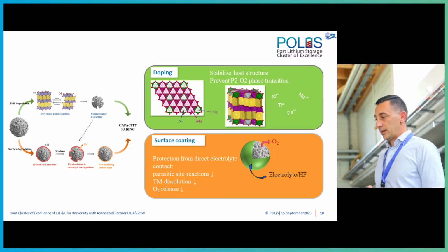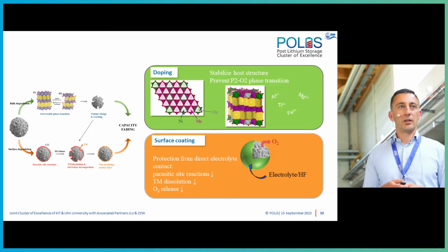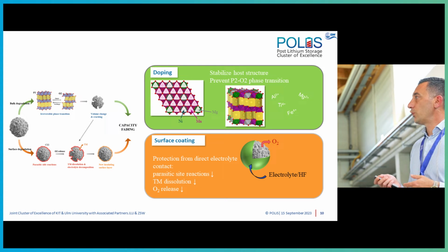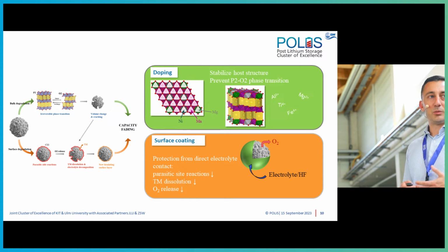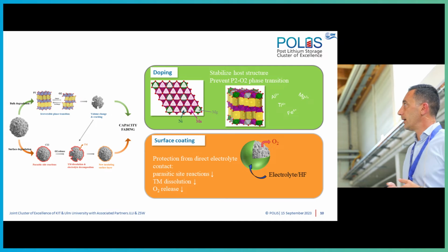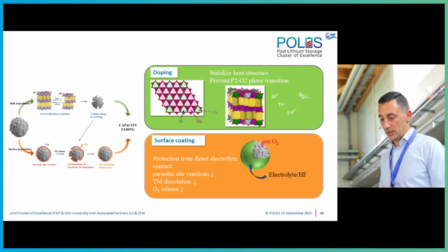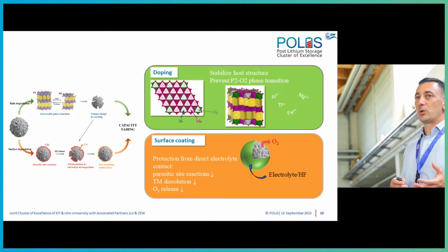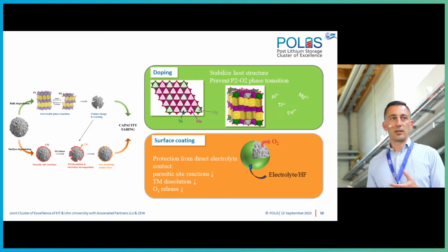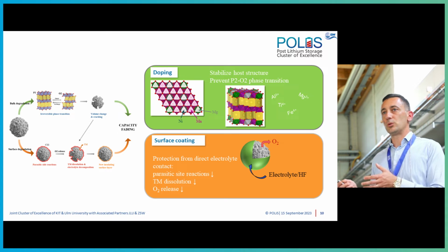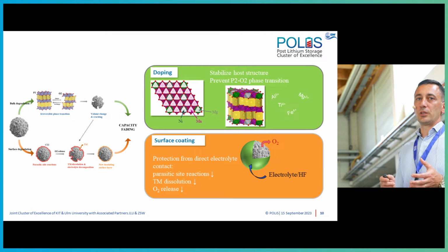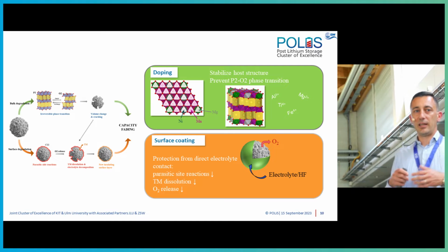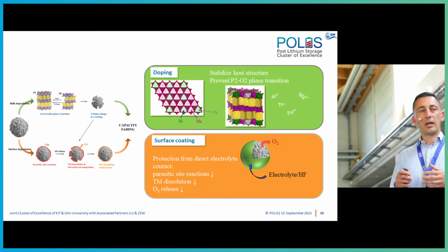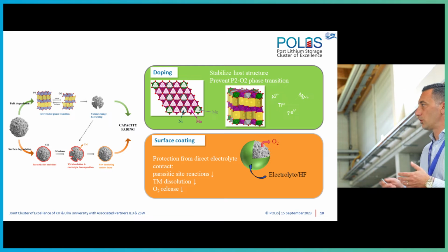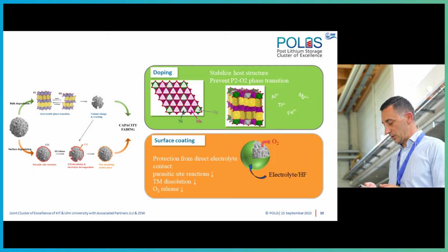Now, going back to the degradation mechanism of the layered oxides, we might come up with different strategies to mitigate the capacity fading. There have been several reports in literature for doping, but also for coating. Now, with the doping, what we are trying to do is to stabilize the bulk, so to prevent the P2 to O2 phase transition. With the surface coating, what we are trying to do is to prevent any side reaction happening at the surface. So we actually followed both approaches, and this is what my talk is about today.